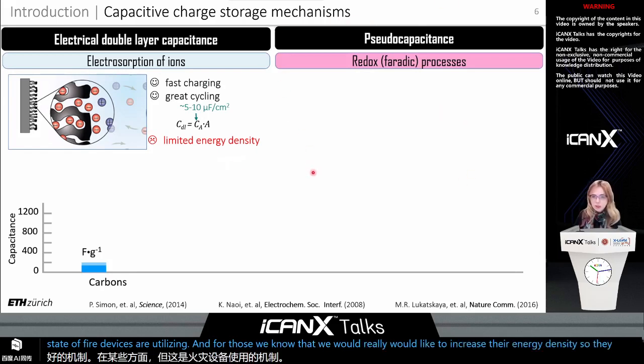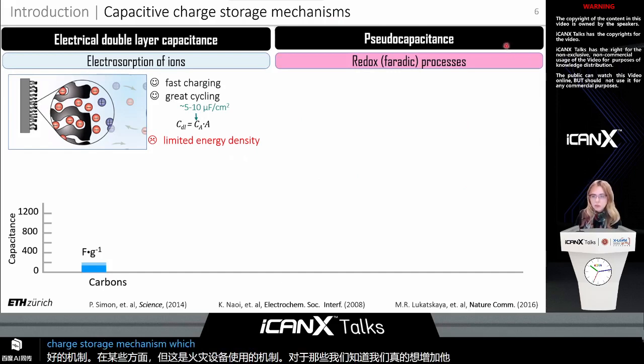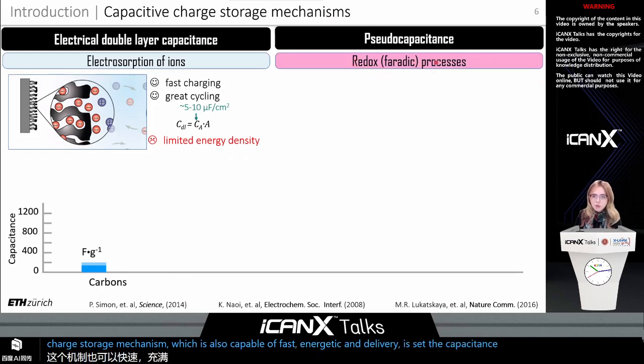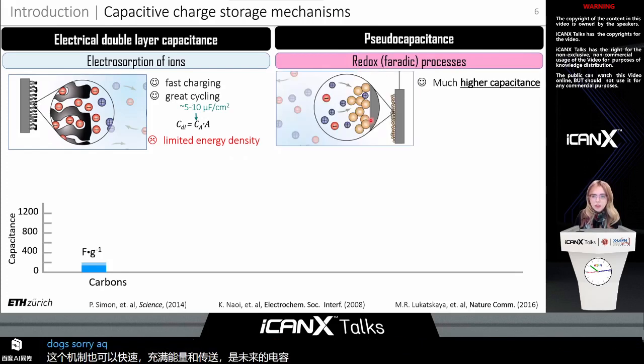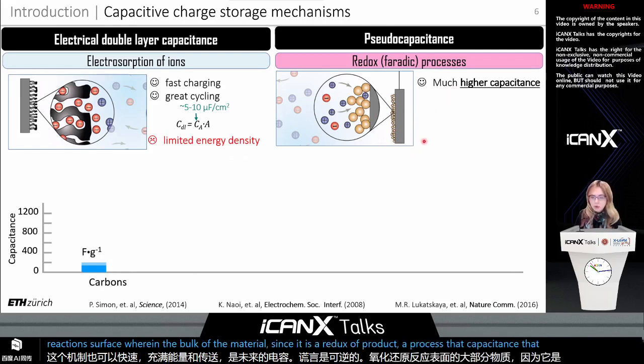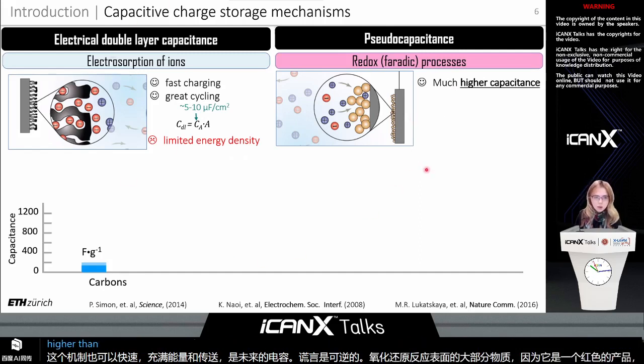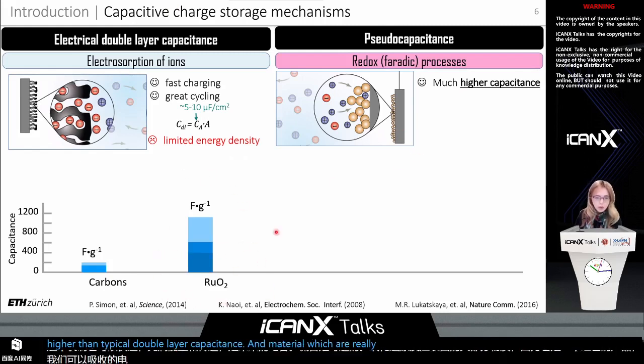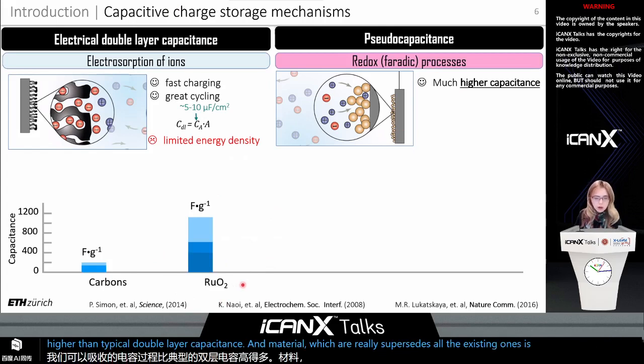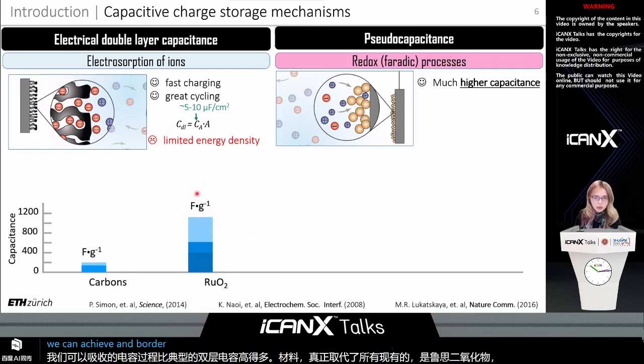So the other charge storage mechanism, which is also capable of fast energy uptake and delivery, is pseudocapacitance. It utilizes reversible redox reactions at the surface or in the bulk of the material. Since there is a redox or Faradaic process, the capacitance that we can observe is much higher than typical double layer capacitance, and the material which really supersedes all the existing ones is ruthenium dioxide, with which we can achieve an order of magnitude improvement in capacitance and therefore energy density.